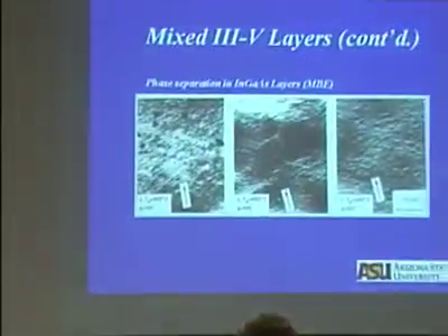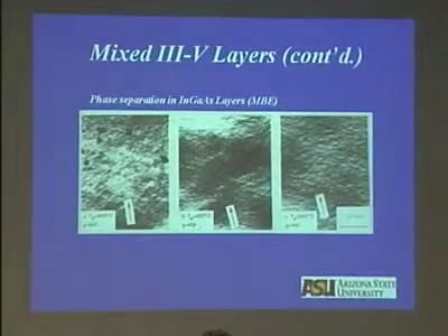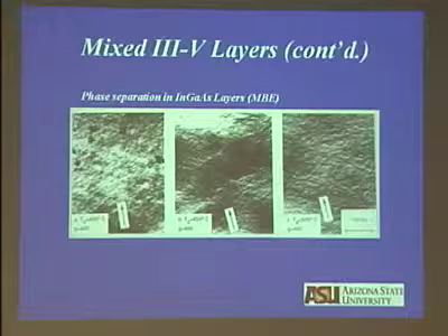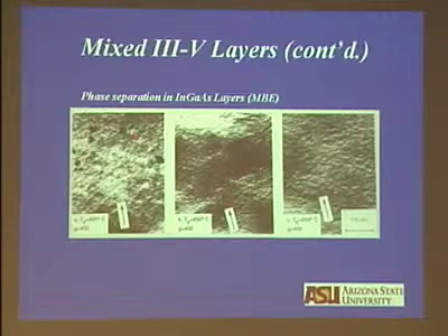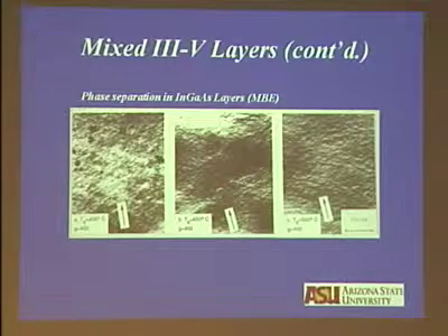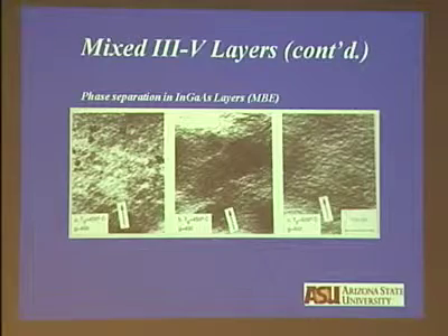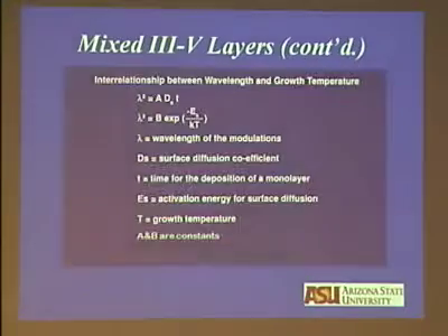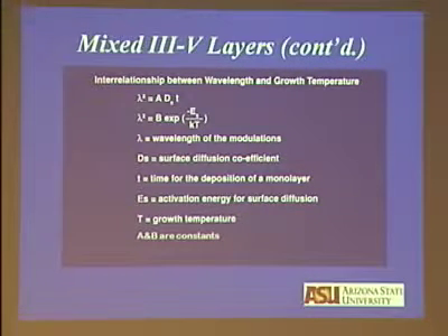Now, people used to argue that phase separation occurs in LPE because it's an equilibrium technique. LPE means liquid phase epitaxy. We had to prove that point, and that is not true. We then did MBE growth of indium gallium arsenide on indium phosphide at different temperatures. These are the reflections we are using, 400, 450, and 500. And you see the speckle structure in all of these layers. We can determine the wavelength from the position of the satellites, and those results we can explain. But let me first give you the development of how the wavelength and amplitude develop in these materials.